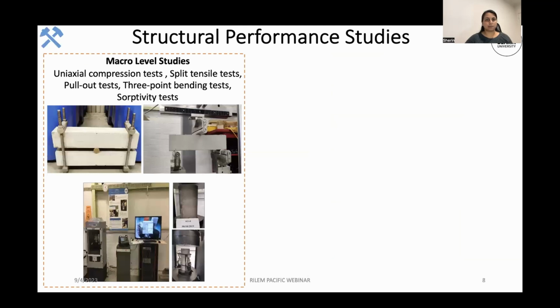In the structural performance studies, we have made use of three types of studies. One is macro level studies, micro level studies, and the modeling studies. In the macro level studies, we make use of tests including uniaxial compression test, split tensile test, pull-out test, three-point bending test, and sorptivity test. The type of specimens that we use for this study is beams as well as cylinders. In the picture shown here, we can see that the beams are mounted on each other, and this is representing a sustained loading that is equivalent to the service loading conditions.